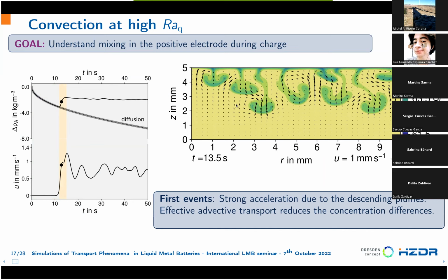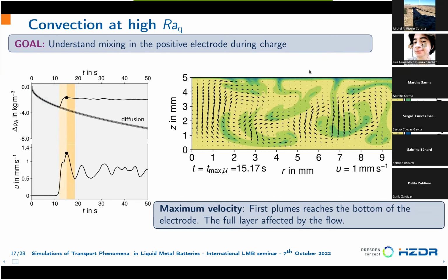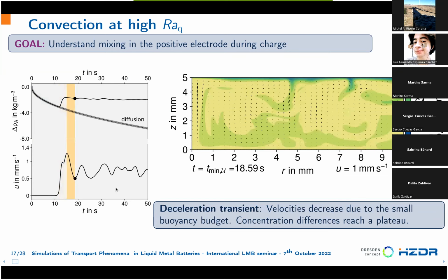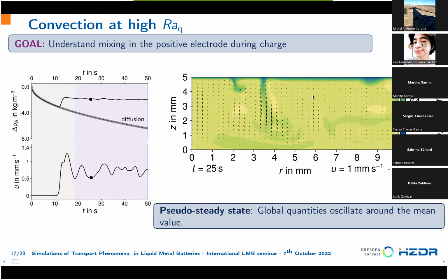And the effective advective transport here is able to reduce the concentration difference and, with the penetration, generates this strong acceleration in the flow. Then the maximum velocity is reached. The full layer is now involved by the phenomenon of solutal convection, and we reach a plateau in the concentration. Instead, the velocity then decreases, so we have a deceleration transient, and then we move to a steady state condition in which the global quantity oscillates around the mean value.